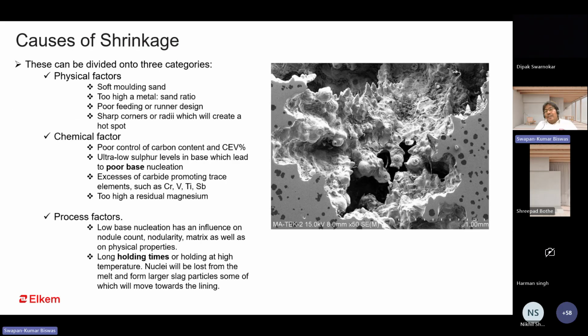So there are three different categories of shrinkage. One is physical, then chemical, then the third is process related. In physical, that will be the mold or your gating system, sand metal ratio. So this part needs to be taken care of to overcome the shrinkage related issue. In case of chemical factors, carbon equivalent is the most important, along with other trace elements, especially chromium, titanium, vanadium, antimony. All these trace elements need to be considered.